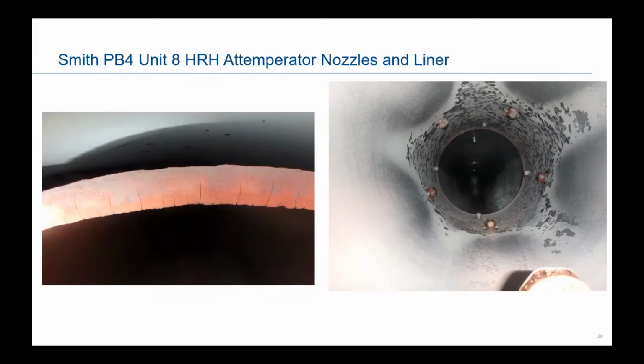Yeah, so we've done that twice now. We did one after a short 6-month install time, and then we installed another set of nozzles for, I think, the next 18 months. Eugene, you can confirm me on that. And then both times we pulled those nozzles and we did X-rays, and we sectioned them and did surface examination looking for any kind of crack initiation, and found nothing in the nozzles at that point. So the longest service life of nozzles that we have been able to destructively test has been 18 months.